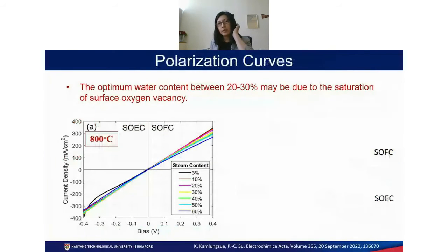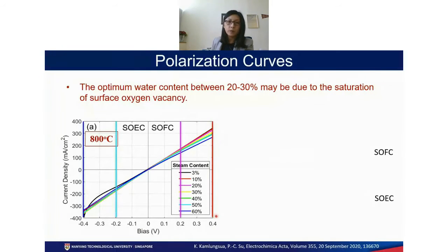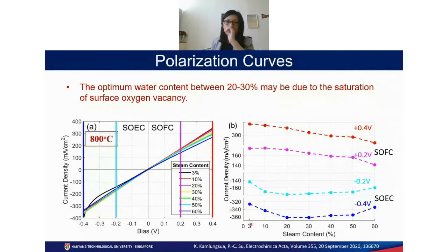Okay, so this is the IV curve, the polarization curves. So, this is for all the moisture contents. Okay, and this is applied bias. So it's probably a bit hard to differentiate. So we just extract the values at 0.4, 0.2, and minus 0.2, minus 0.4. So meaning that 0.4 SOFC and 0.4 SOEC. And then we see how the current density is changing with moisture contents.